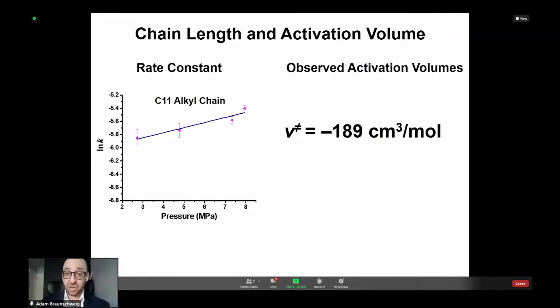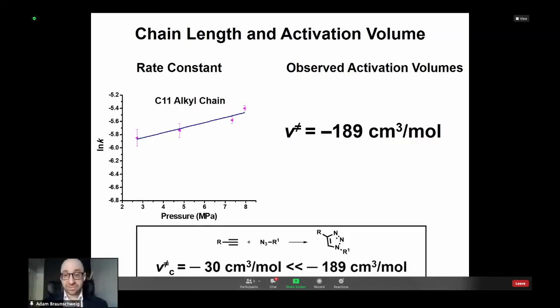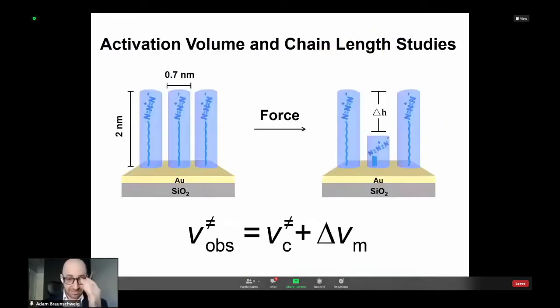Okay, so we took this plot, we got an activation volume out of the reaction. However, these old studies included a study of the Huisgen reaction, and the activation volume was known to be about 30 cm3 per mole, whereas we measured something approximately 5 times or 6 times greater than that. So where's the discrepancy? Why is the activation volume on the surface so much larger than the activation volume in solution? So we made the following postulate or hypothesis.